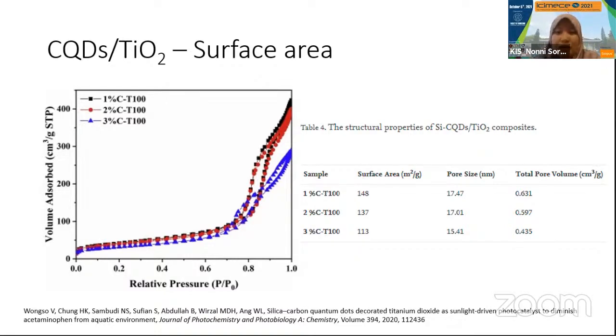So what we see from here is maybe there is agglomeration during the mixing process in the precursor step. The mixing process might not be well distributed because the carbon quantum dots themselves tend to aggregate to each other, right? So if we increase the amount of carbon quantum dots, we think that we might get high agglomeration that decreases the surface area of the composite itself.